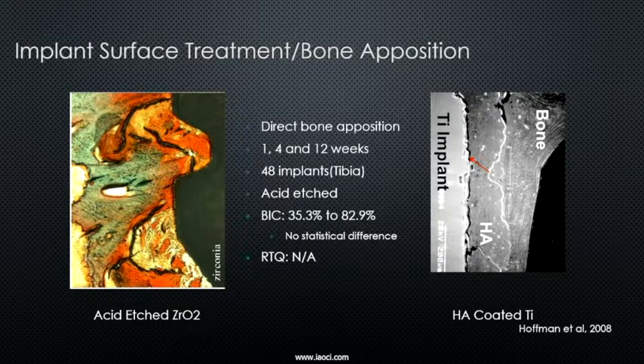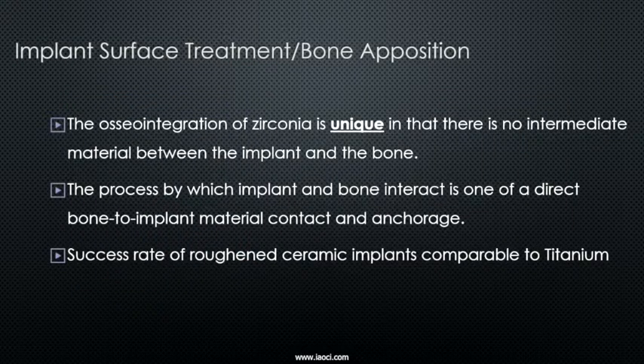It doesn't mean ceramic implants don't fail. That's not what it means. It just means that it's a different process of osseointegration, and they both work. So the osseointegration of zirconia is unique in that there's no intermediate material between the implant and the bone. And the process by which implant and bone interact is one of direct bone-to-implant material contact and anchorage. And the success rate of ceramic implants is as good and comparable to titanium.